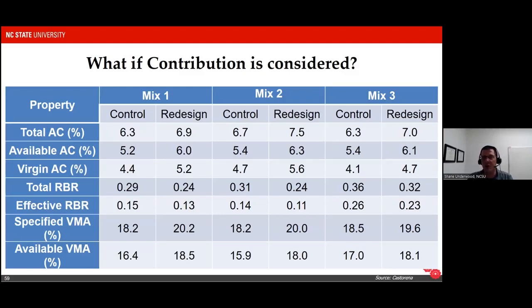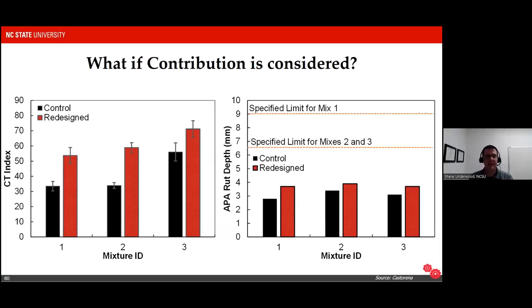This was not simply changing the binder content, although one could do that, but in fact adjusting the gradation to match and yield an acceptable volumetric combination and concentration. And then what she found was actually, as judged by the CT index, she could actually increase the amount of RAP material in the mix and at the same time improve the performance of that mixture. So the offshoot of this is that it is possible, there is evidence of using recycled materials, designing them very carefully to ensure that their performance is not negatively affected.